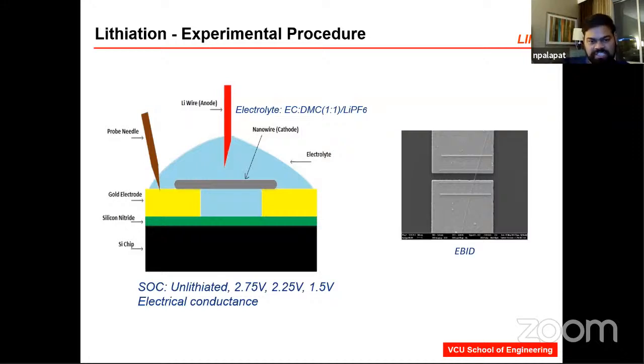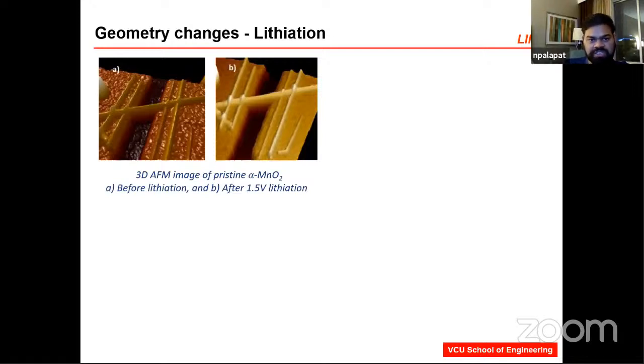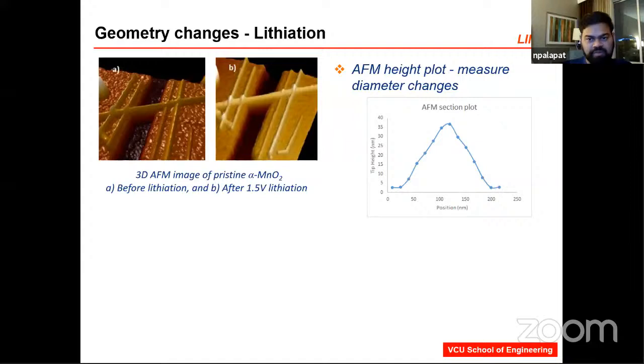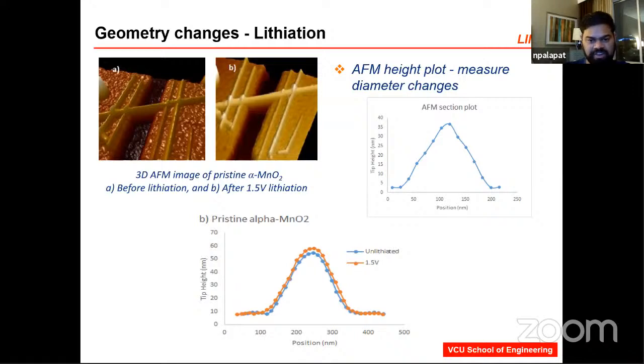So we saw that example of the TEM, where during lithiation, the nanowire experiences a lot of structural changes. To determine these structural changes during lithiation, I've opted for using the atomic force microscope. In this figure, as you see on the left, is a pristine nanowire, pristine in the sense it is as synthesized. Then the next one is post lithiation. And I've used the AFM plots to measure the diameter of a nanowire. This is how it would look between lithiated and unlithiated nanowires. You will be able to clearly figure out that the nanowire keeps changing in size when you start lithiating a nanowire.